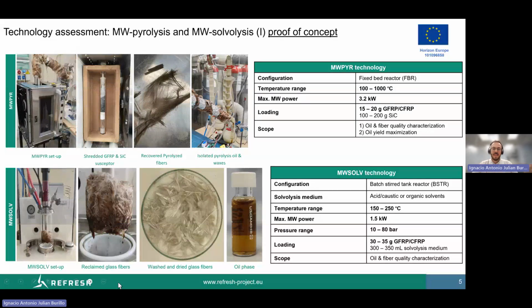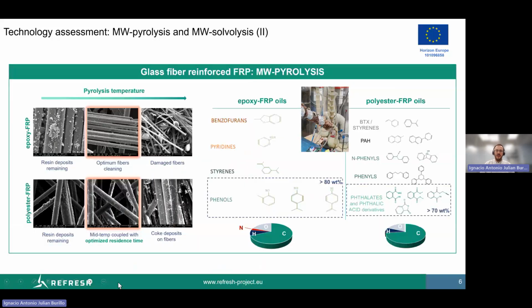separate fibers, but they become coked unless we use a kind of a combustion step to remove these carbon deposits. While under solvolysis, we are getting clean fibers and oils. The quality of oils will be compared later. So under pyrolysis, we were processing both epoxy and polyester composite resins. And we found that the most impactful parameter in the process operation is the pyrolysis temperature.